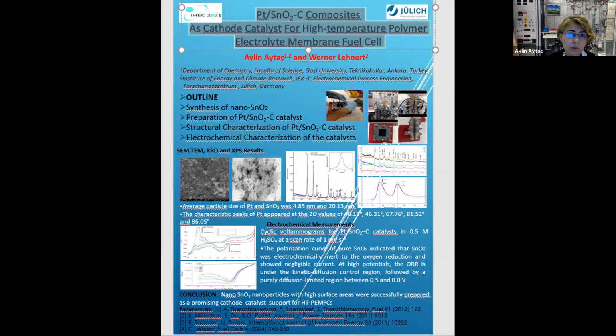When the catalyst contained a higher concentration of tin oxide, the performance decreased as a result of the mass transport limitation within the electrode. Durability tests showed that tin oxide carbon supported platinum catalysts prepared in this work were stable under the fuel cell working conditions during 350 hours at 160 degrees centigrade, demonstrating a potential cathode catalyst for high temperature PEM fuel cell.